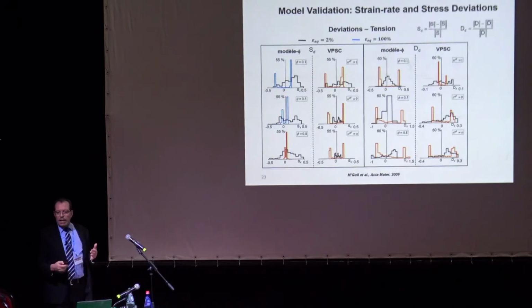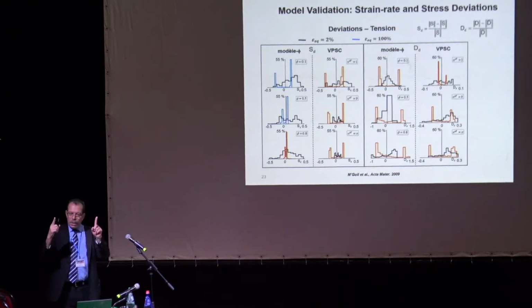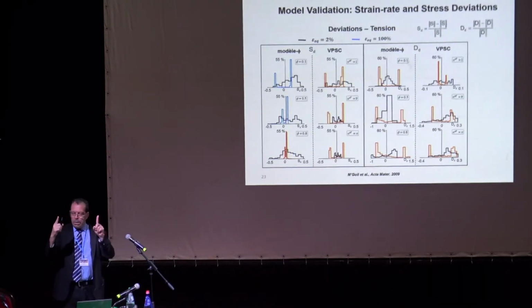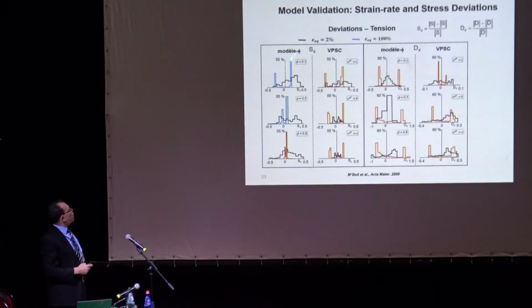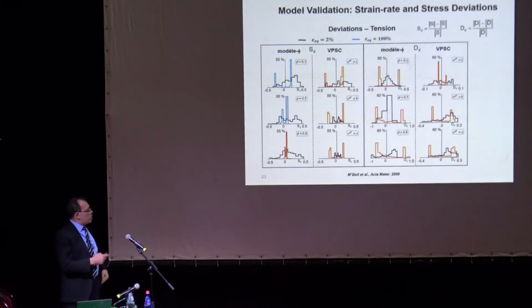So we started with the random, so no surprise to see something more or less spread out. Whereas if you go to 100% strain, where the material becomes highly textured, then you can see, this is tension, you can see 2 peaks, in fact. This is because, as I showed you, there are two components of the texture, 2 preferential orientations. That's why you see those 2 peaks, okay? And we see them for stress, we see them also more clear in the strain distribution. And again, we can compare here the tangent modulus versus the secant modulus versus different phi and so on.